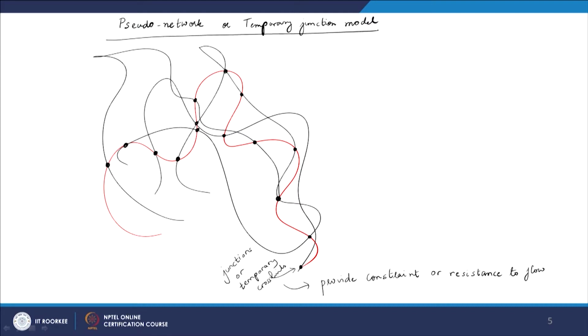So, the advantage of doing that is now I can start using the ideas we have developed in the case of a rubber, the polymer network, to analyze the behavior of these entangled systems with only one additional thing, that is the cross links in this case are not permanent as opposed to what we have assumed in the case of rubber. Those were chemical cross linkings. These are some sort of a physical cross linking that can change, or the polymer chains can really slip through the junctions, so to speak.